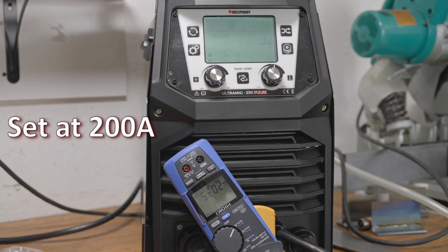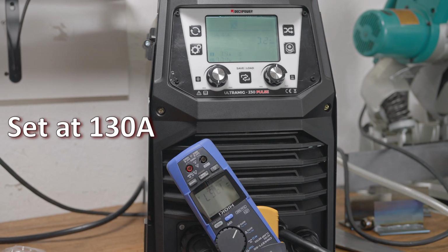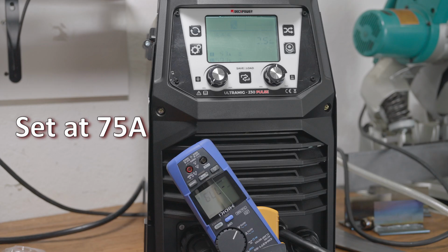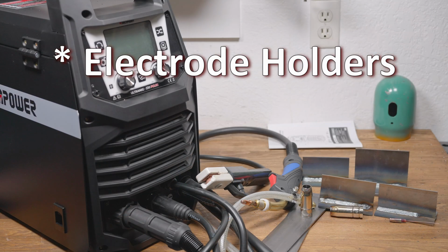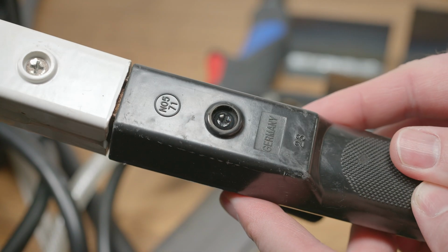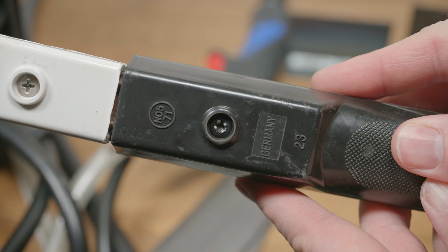I did test the stick welding mode, and I thought I saw somewhere that the max output in stick mode was 180 amps, but it actually goes up to 200 amps, and it can put out the full 200 amps. And at all settings, the output is close enough to the setting that I could pick a rod, set the amperage, and it would run as expected. The bulky electrode holder isn't my favorite, but it worked okay. Ironically, this is one of the only stick electrodes that ever inadvertently arced out on me while I was setting it down, and it wasn't even in the front where I broke the insulator. It was actually at this screw.